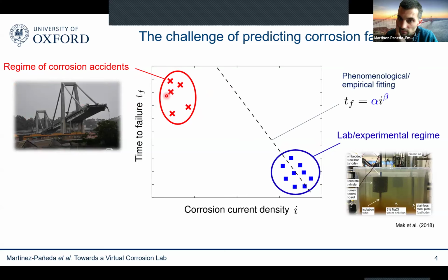Of course, you can always interpolate data, and to a certain extent, you could argue that computer models have always existed in corrosion, in the sense that there have always been experimentalists that run a few experiments, draw a line through those experiments, pick their favorite polynomial, and then come up with some sort of empirical or phenomenological law where they say, okay, my time to failure is related to corrosion current density through some magic empirical parameters, alpha and beta, which have no physical meaning. I'm just going to fit the data and hope that what works here is also going to tell me what happens here. But that, of course, is a challenge because the conditions are very different and because the physics are very different in this accelerated corrosion test than what happens over decades. So that's a problem.